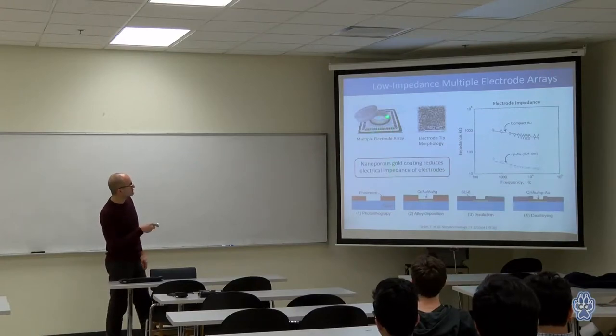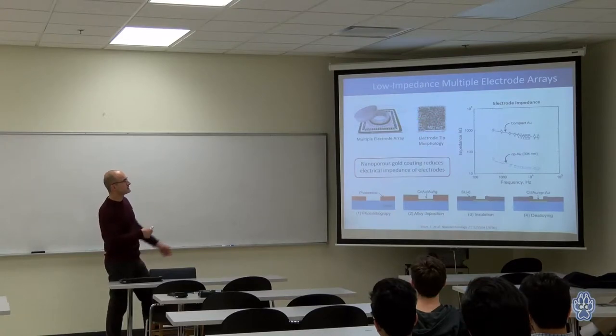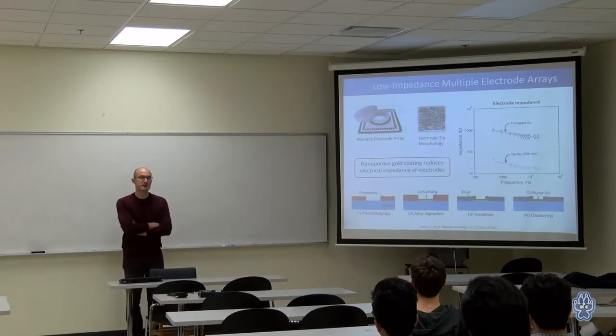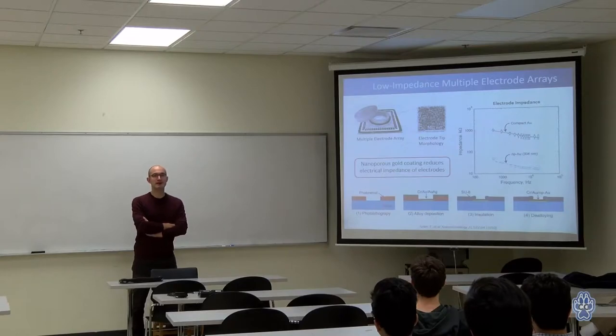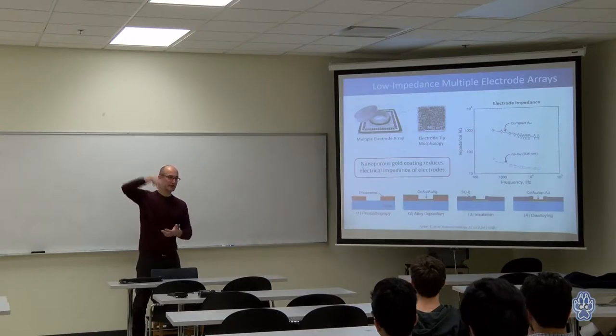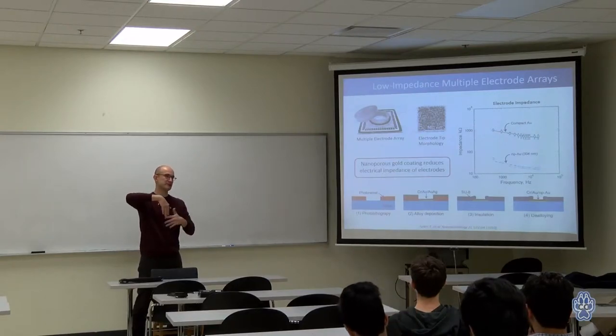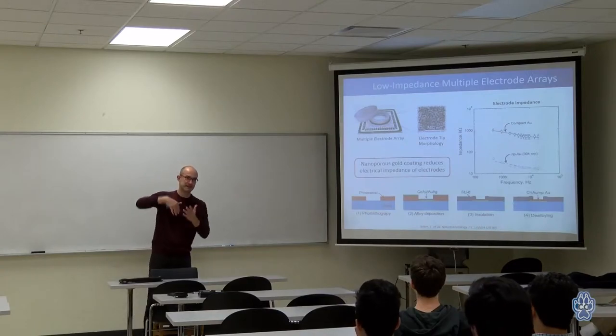So you have these electrodes, and you have the tips, and they are porous. So we measure the impedance. The impedance in the biological system is more electrochemical impedance. You have an electrode immersed in a solution, and we are measuring the impedance at that interface.